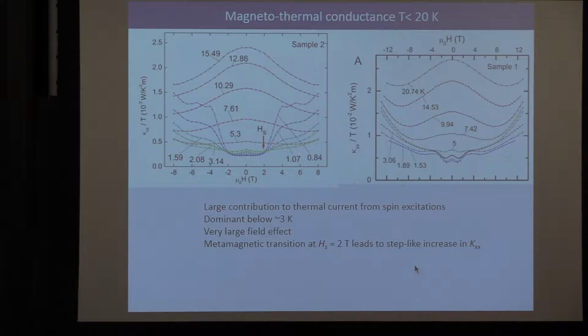And this was actually detected by neutron scattering, that if you look at neutron diffraction, the Bragg volume is completely uniform and featureless in zero field. But when you apply a magnetic field, the diffraction pattern condenses into a bright peak, which indicates field-induced ordering. And we think we're seeing the same thing in the thermal current. So this would appear to signal the existence of spin waves in this ordered phase that's field-induced, right?